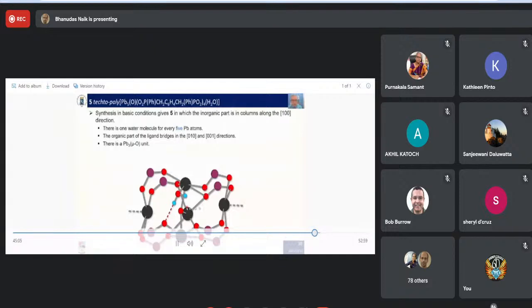And basic condition shows us this compound here, which has this oxo. The oxo ligand here is between 3 lead centers in a slightly basic solution. So this is something you have to watch out for with these compounds. And this is also a three-dimensional coordination polymer, where you have this direction here, and the next direction you have a phosphonate patch bridging the lead centers, and you have the phosphonates joined by the organic connectors in the Y and the Z directions.